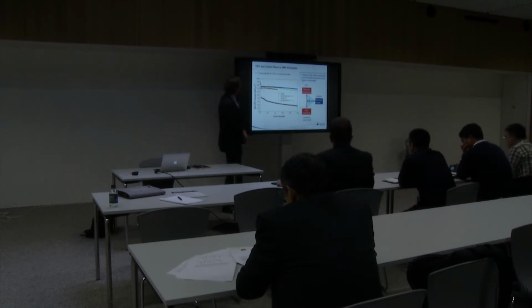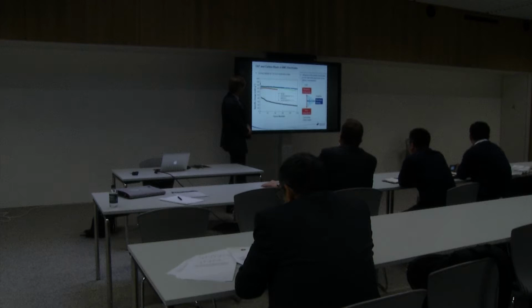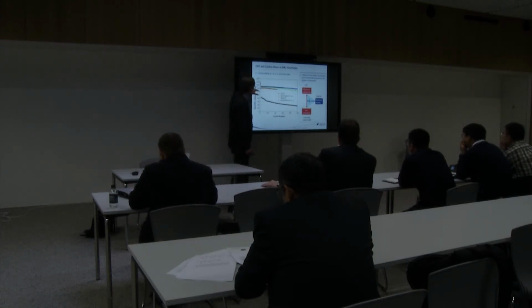The slide here shows cyclic stability at 1 weight% of conductive mass, so this is relatively low. It's basically where the conductive carbon black is already pretty high in the percolation with regards to the electrical resistivity. What you see here is that, of course, the pure carbon black shows a relatively bad cycling stability, but at the same time, when working with mixes of carbon black and multi-wall carbon nanotubes, the cycling stability can be optimized.